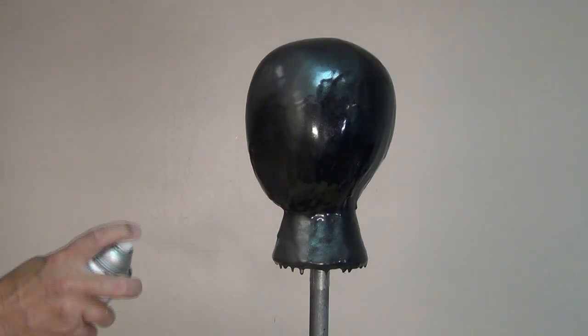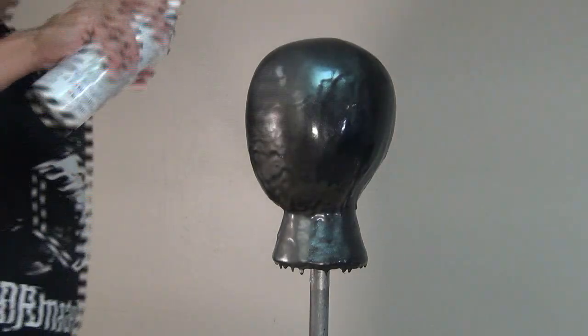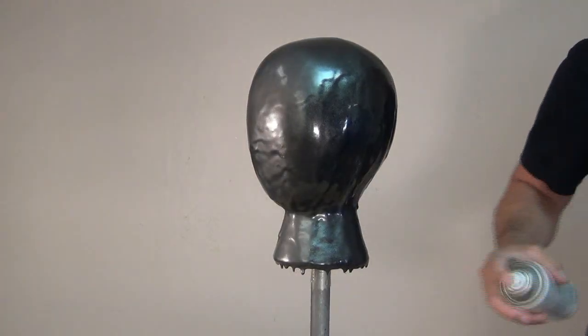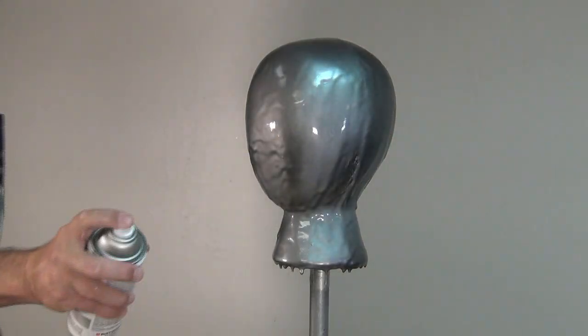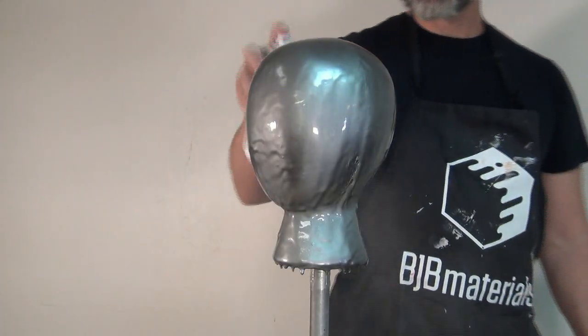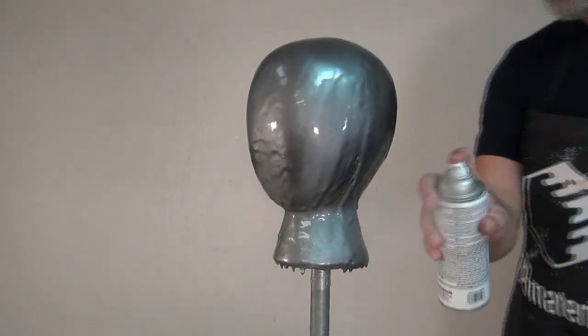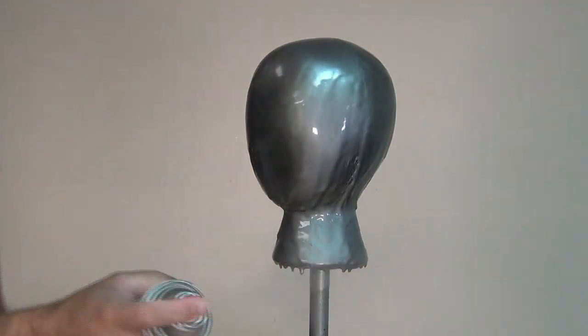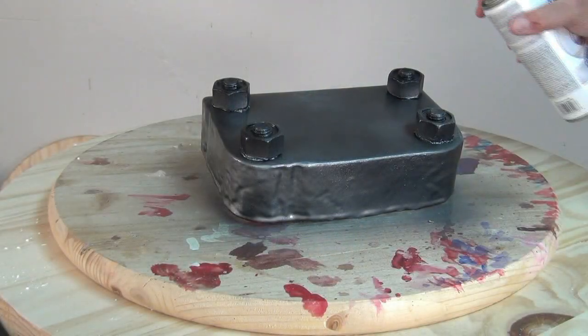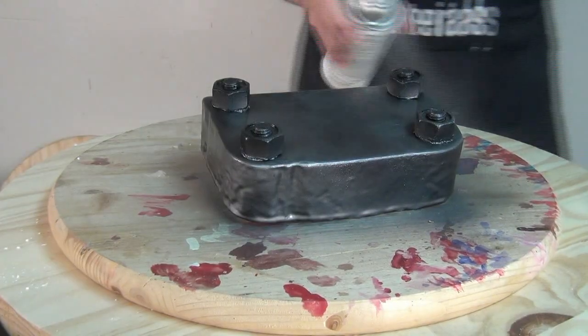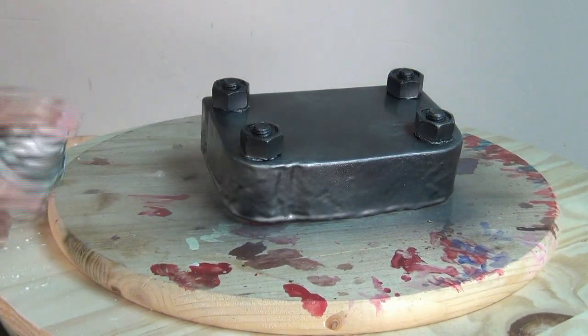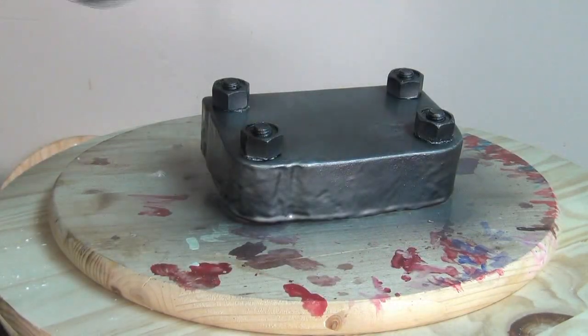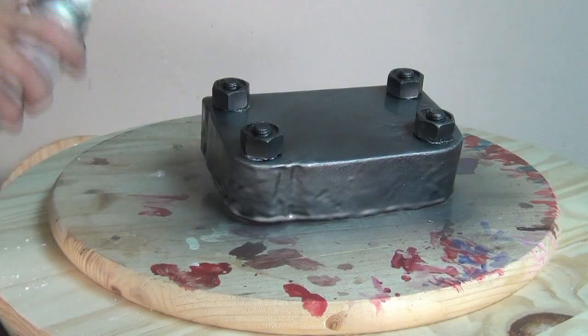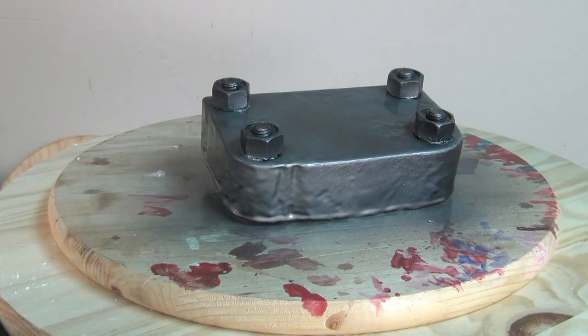Again, I figured that black base coat would be a good metallic undercolor, and just hit that with the silver spray paint over the top. And I got a surprisingly good bond between this super duper cheap spray paint and that resin surface. And as many of you know, that is definitely the exception to the rule. Most of the times when you paint a polyurethane resin like this, you don't get that good of a bond. So excellent adhesion of just regular over-the-counter paint. And overall, I think these were pretty good results, which is why I am sharing them with you now, dear viewer.